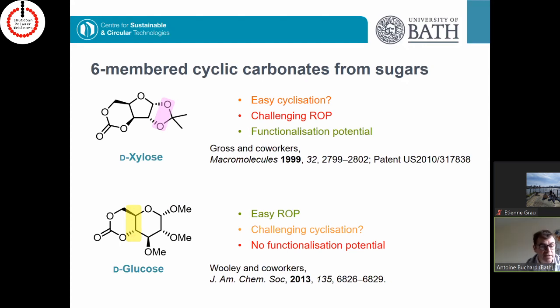We have this idea, but this was something that had been done in the past as well, and this has to be acknowledged. The first couple of examples of this type of structure had been done by Gross and co-workers, who made this 6-member cyclic carbonate from sugars, in this case from D-xylose. And they made this beautiful monomer where you had this isopropylidene protected 1,2-diol motif here, which was really interesting to us because that clearly shows some functionalization potential. The only problem with this monomer, if there's any, was that the ring opening itself was a bit challenging, and this is certainly due to the less strained nature of this ring.